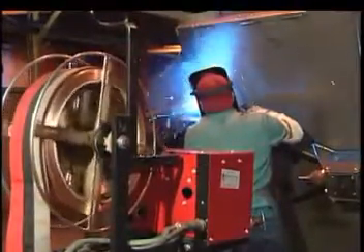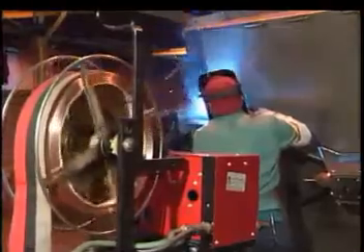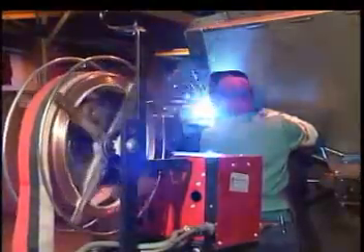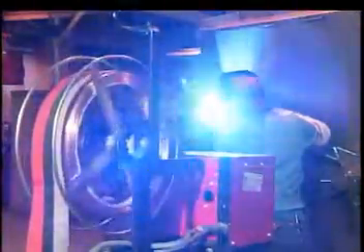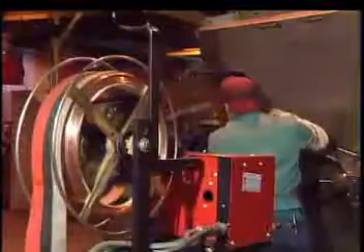Weld out of position easily with the gas metal arc PowerWave process. The arc is very stable. The PowerWave is very effective for welding steel, stainless, aluminum, and most alloys. The pulsed spray arc is as stable as a converted spray arc. The pulsing process transfers small droplets directly through the arc, one droplet during each pulse. As the wire is advanced, the current pulses and transfers the next droplet.